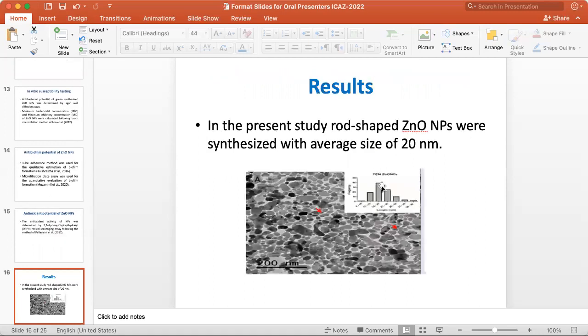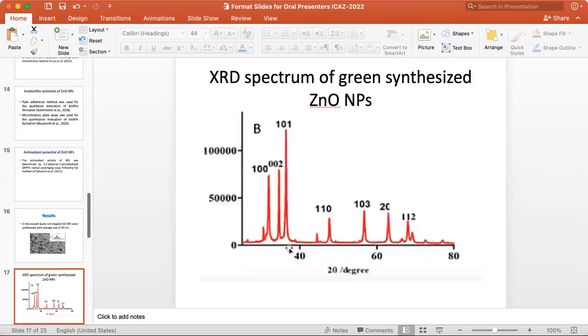Here are the results, and you can see here this is a micrograph of zinc oxide nanoparticles. Most of the nanoparticles were rod shaped, and a few nanoparticles have a hexagonal shape. So rod to hexagonal shape nanoparticles were formed, and the average size of the synthesized nanoparticles was around 20 nanometer. The XRD spectrum of the nanoparticles has also been shown here.